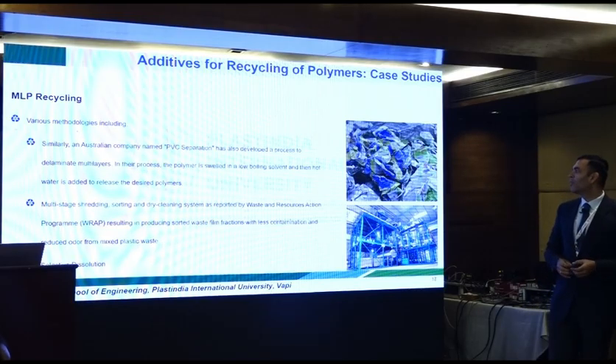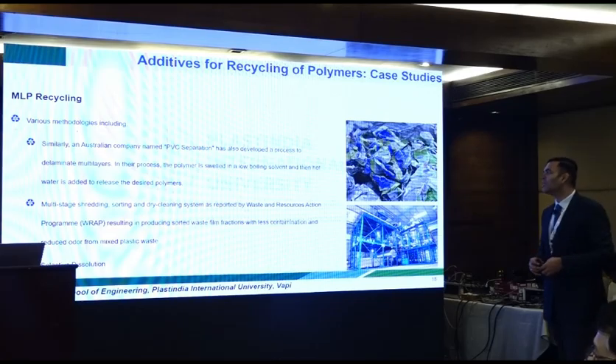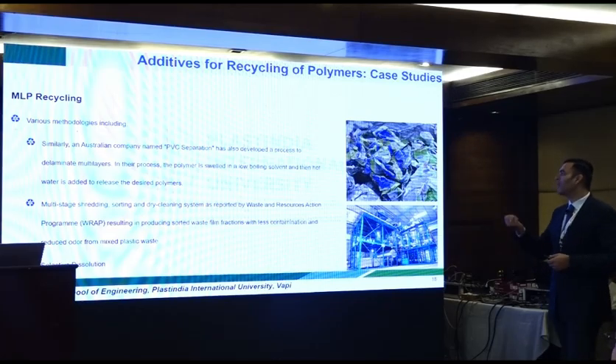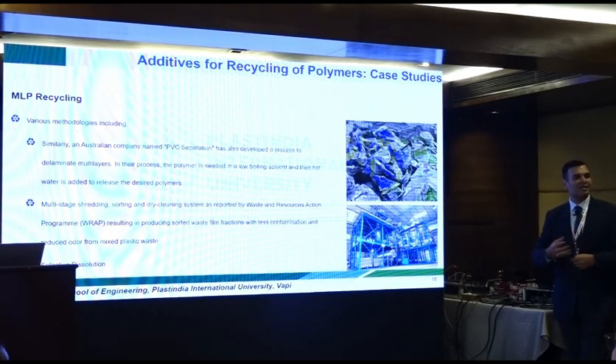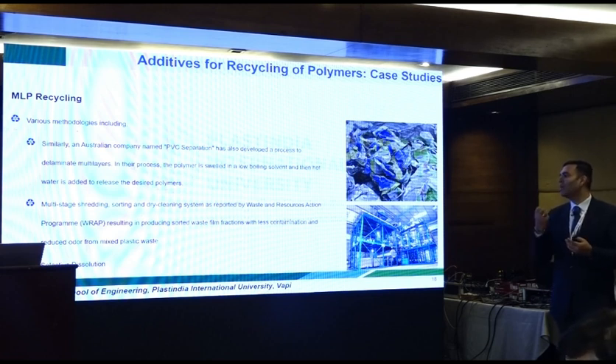An Australian company called PVC Separation has developed a product to delaminate multi-layers. In their process, the polymer is swollen in a low boiling solvent and hot water is added to release the desired polymers. And then multi-stage shredding, sorting and dry cleaning system are also reported by WRAP, which results in producing sorted waste film fractions with less contamination and reduced odor from mixed plastic waste. There is a process of selective dissolution as well that can be done.